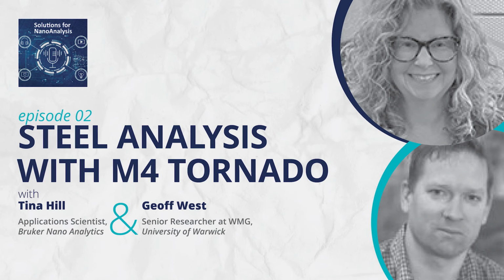So after you did some characterization for them, how did they use that information? Were they able to pinpoint maybe some areas that they wanted to get a much better feel for? So the project we're doing with Tata is still quite early days, but we're using the XRF to basically, at the moment, pinpoint areas for more detailed study for other techniques. Sure. And that's one of the things, the XRF tells us where to look. Instead of a needle in a haystack, we know this area has this grain structure and has this composition. Right. Instead, you've got the helicopter view of what's going on.